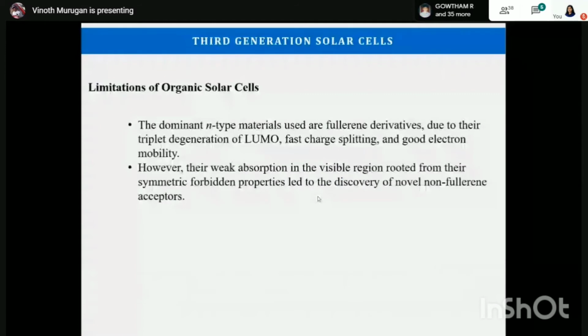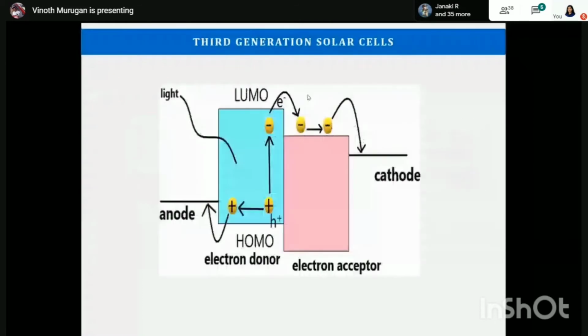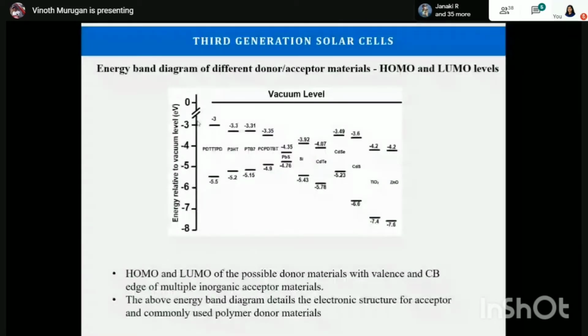Then I shifted to 90% aluminum electrode with a 10% calcium interfacial layer, because it observes the electrons from the active layer so fast and quickly. It reduces the recombination rate. So I introduced a 10 nanometer calcium buffer layer above the active layer, and also for reference I added 20%, that means a 20 nanometer calcium interface layer with an 80 nanometer aluminum layer. Then I went to characterization.